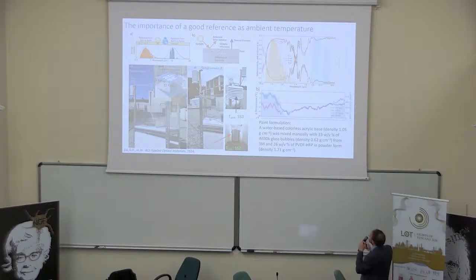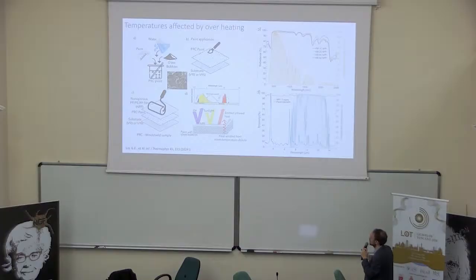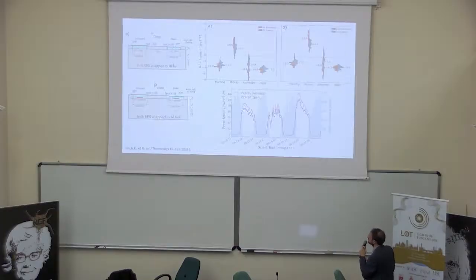And there are the optimal properties of these kinds of materials that we made here in Florence. They are highly effective and highly emissive in this part of the spectrum. All the effects that we studied are related to different properties, but as you can see, it's very hard to go below ambient temperature during midday. Normally, you go down a bit during the other parts of the day.